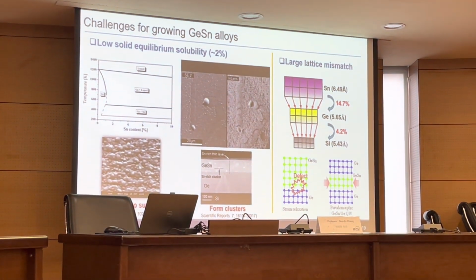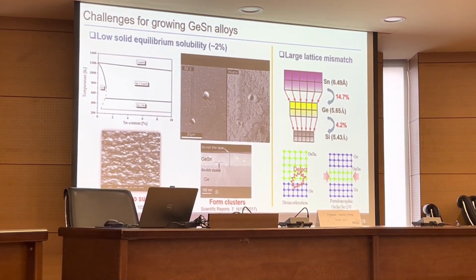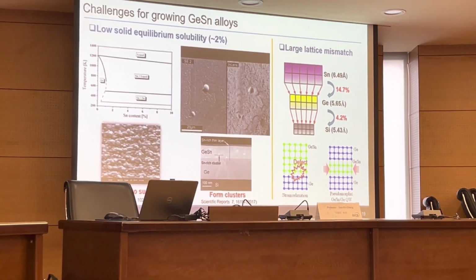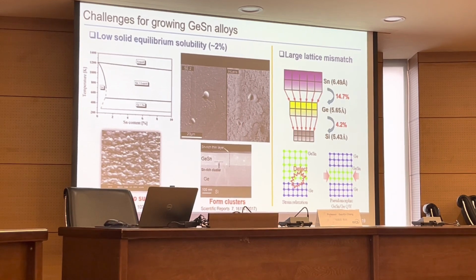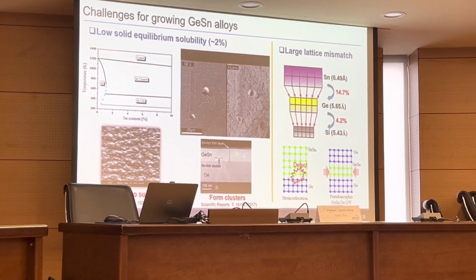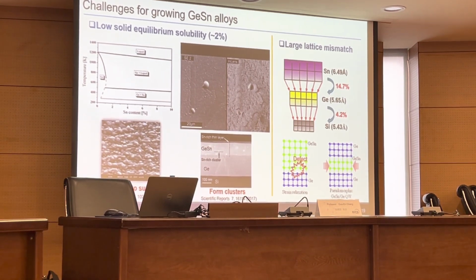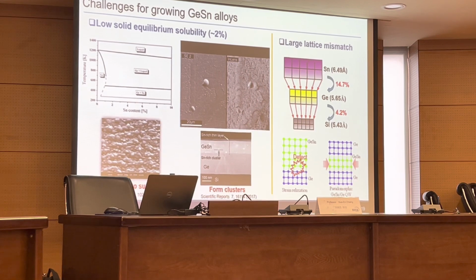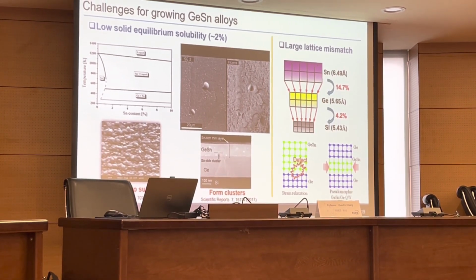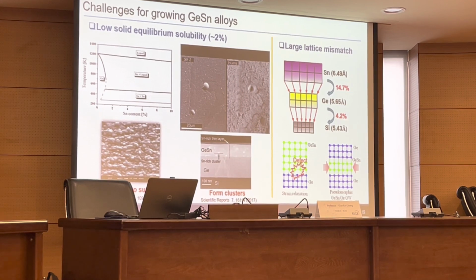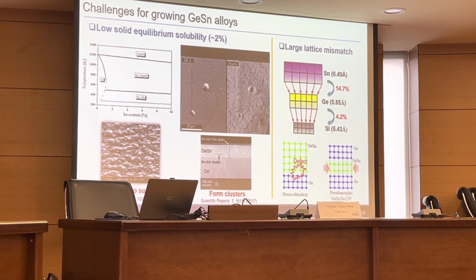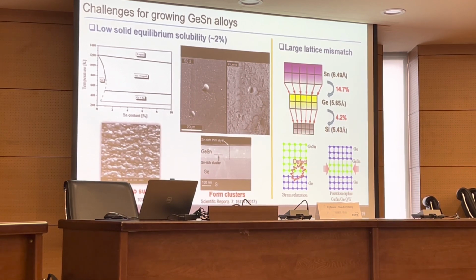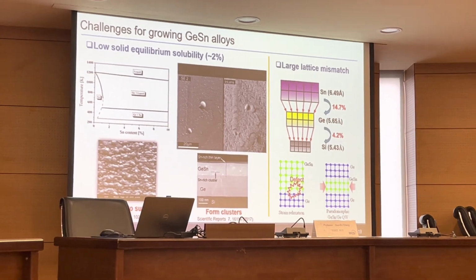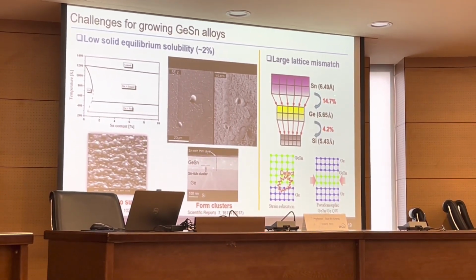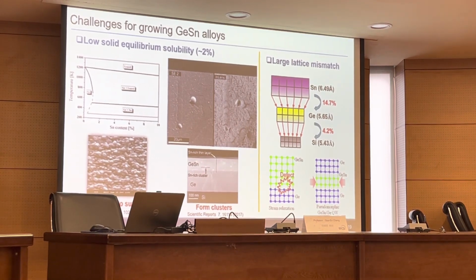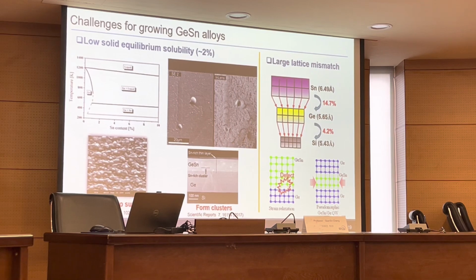The second challenge is lattice constant mismatch. If you take a look at the lattice constant of germanium and silicon, the lattice mismatch is already 4.2%. So it's already very difficult to directly grow germanium on silicon. People have tried to grow germanium on silicon directly, but it takes about 20 years to be able to grow a good germanium layer on silicon. But if we would like to introduce tin into germanium, the lattice constant mismatch is even larger, so it's more difficult to directly grow germanium tin on silicon.